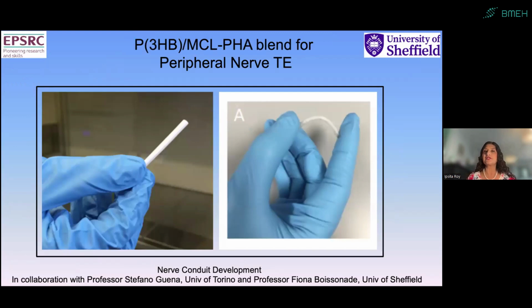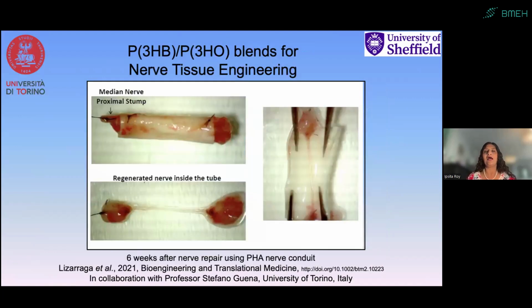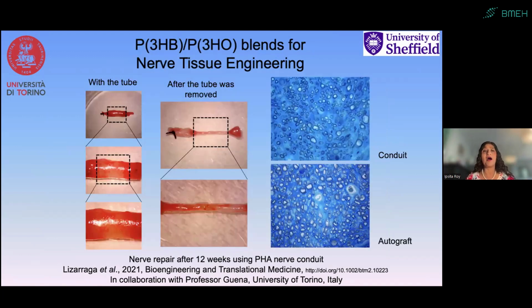So we produce these tubular structures with a medium chain length PHA and P3HB blend, and you can see here how beautifully they caused a regeneration of the nerve within 6 weeks. So the suture, you can see, attached the nerve conduit, and the nerve then grew back within 6 weeks. And here is the nerve after 12 weeks. They are very well regenerated, and with the conduit, we got the regeneration, as you see on top, the nerve guidance conduit, which is that tubular structure that I mentioned to you.